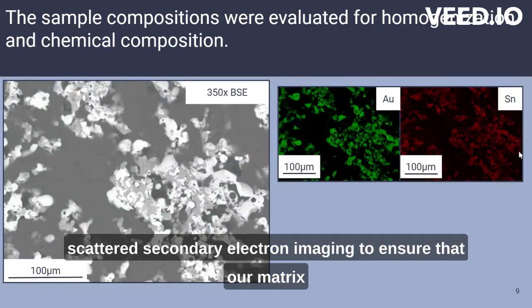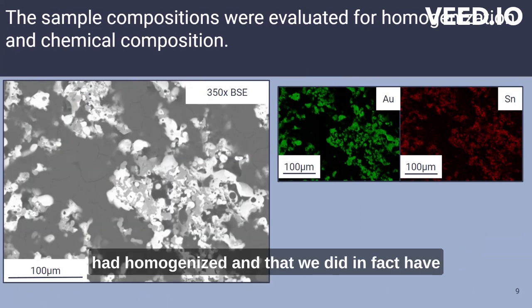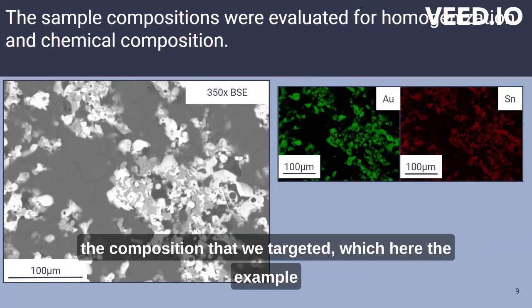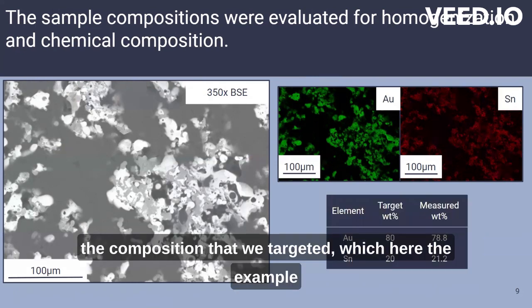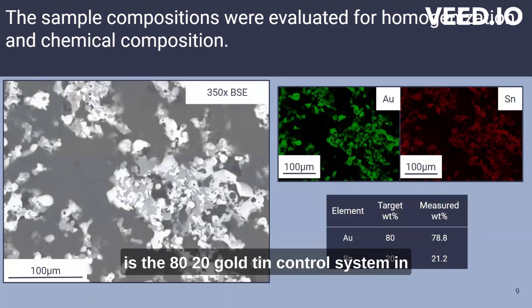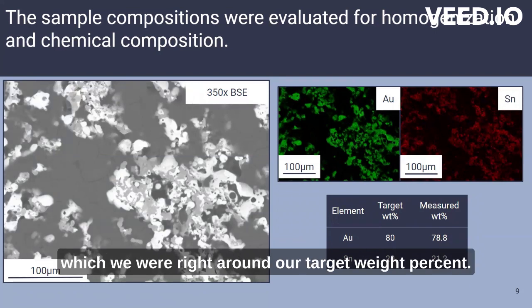We used backscattered electron imaging to ensure that our matrix had homogenized and that we did in fact have the composition that we targeted, which here the example is the 80-20 gold tin control system, in which we were right around our target weight percent.